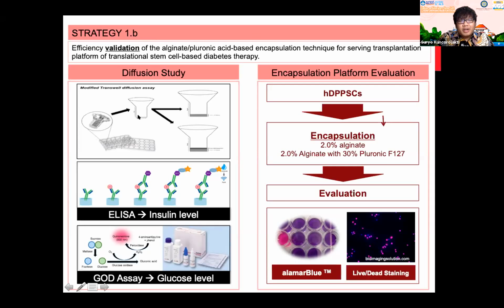And to evaluate the diffusion study, we use glucose and also insulin solutions, to check the level of glucose and also the insulin. For the insulin, we use the ELISA, while for the glucose, we use a glucose oxidase assay to check the glucose level. And for another evaluation of the encapsulation platform, we tried to encapsulate undifferentiated dental pulp stem cells, and then keep them in the media, and then evaluate the proliferation with the Alamar blue and also confirmation test with the live/dead staining.